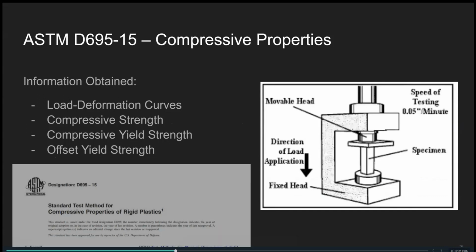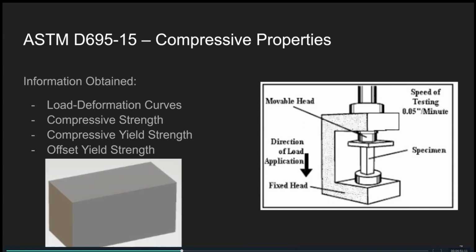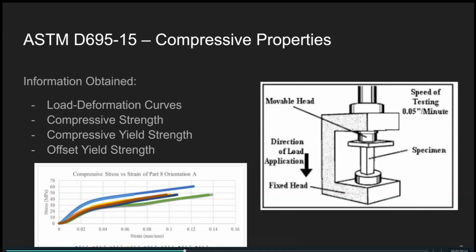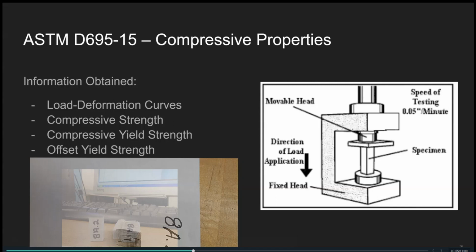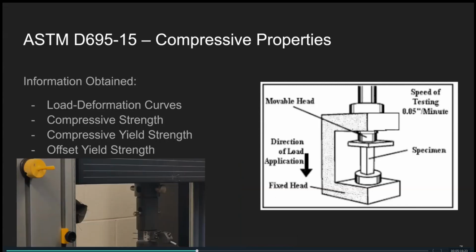Next up was ASTM D695, which is compressive properties. This was similarly run on the Instron, but instead of the wedge grips, compression platens were used to measure the load deformation curves, compressive strength, compressive yield strength, and offset yield strength. Again, no observable yield strength was easily definable on the load deformation curves or stress strain curves. And so offset yield strength was a useful approximation method to find the yield strength on those stress strain curves.